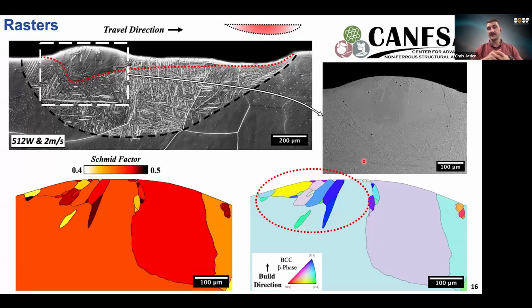But what we actually do see is that the lower Schmid factor grain, so this orange grain correlating to this boundary, actually has the reduced Schmid factor. So it's going back on what we thought, where now these higher Schmid factor grains are the ones that didn't transform. So this caused us to go back and think.